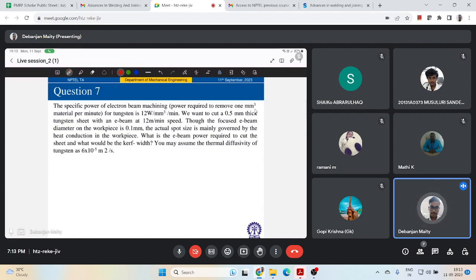Here it says that the specific power of electron beam machining for tungsten is 12 watt per millimeter cube per minute. So I have this specific power as 12 watt per millimeter cube per minute. Then it says we want to cut a 0.5 mm thick tungsten sheet with an e-beam at 12 meter per minute speed. So my thickness is 0.5 mm. My velocity is 12 meter per minute.